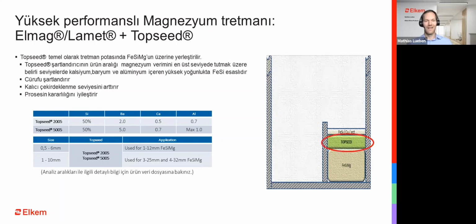Thank you. Let's move over to our cover alloy Topseed. A sandwich cover is recommended to obtain maximum treatment recovery. The purpose is to retain the alloy in the pocket for as long as possible before the reaction starts. Topseed addition compensates a negative effect of magnesium treatment. It will add further inoculation effect. This can be seen in thermal analysis curves.